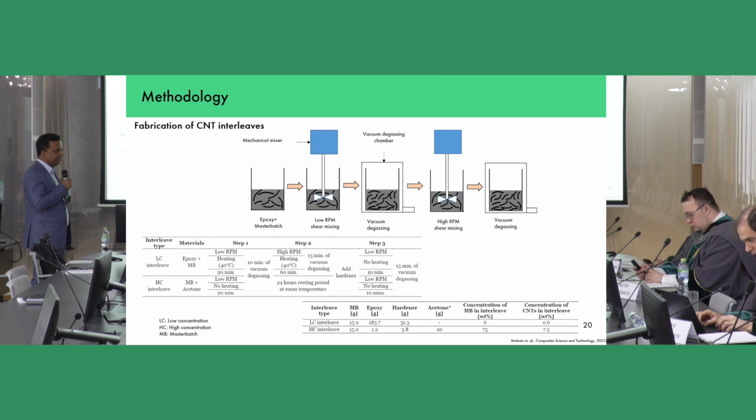Yeah, for toughening effects, no positive result. It was only a reduction in fracture toughness. But for curing, 0.6% was enough to show this property that can be used as a cure monitoring sensor. Yeah, because I think there you showed how the change in resistance followed a similar behavior to the tensile behavior, right? If I understand correctly. Right.